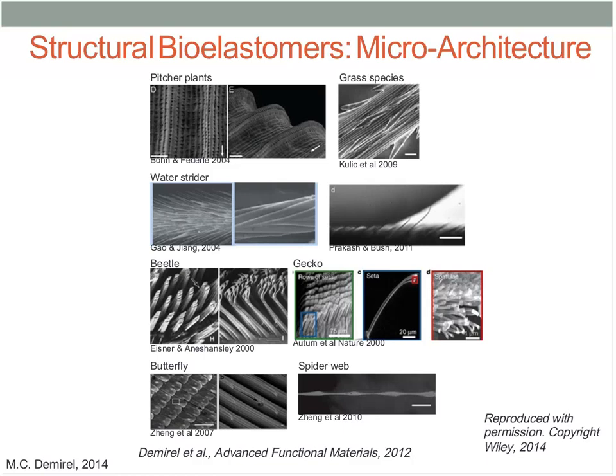The flexible hairs on geckos allow a much greater contact area with uneven surfaces compared to smooth surfaces. The density of hairs on such surfaces scales with the body mass. Insects, for example, have lower hair densities compared to lizards. The force of a single seta of gecko toe pads, measured by using a two-dimensional micromechanical system, shows that the attachment forces are 600 times greater compared to flat surfaces.